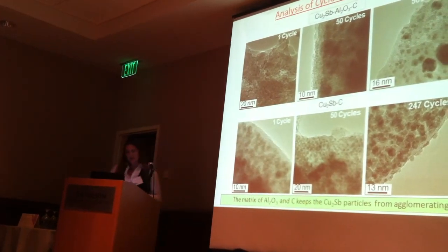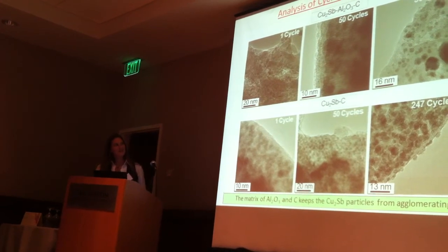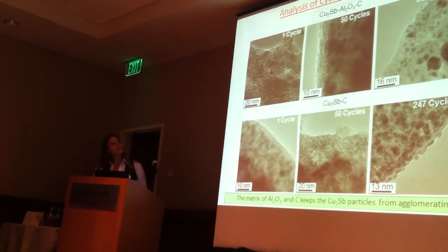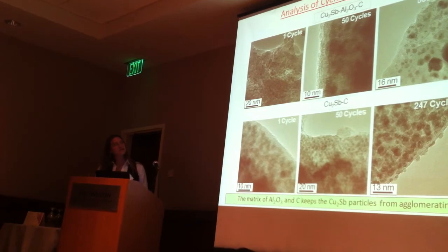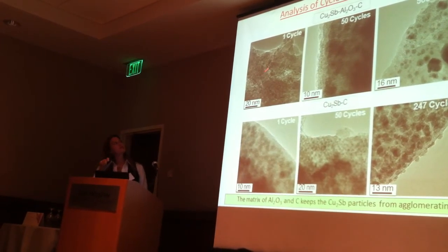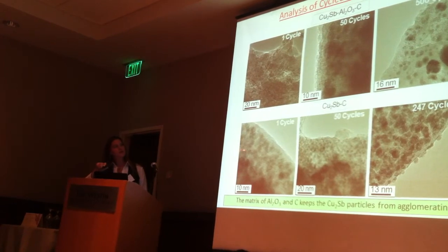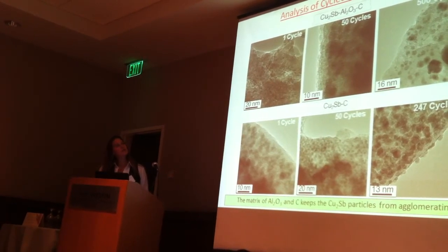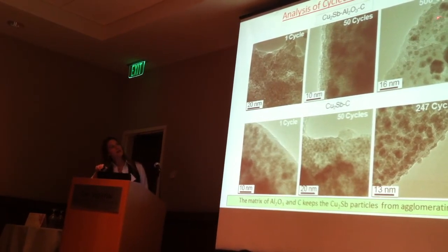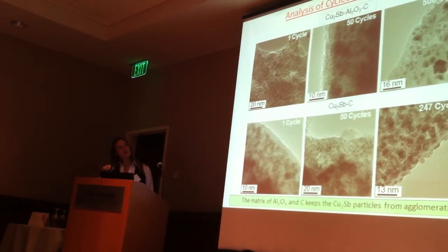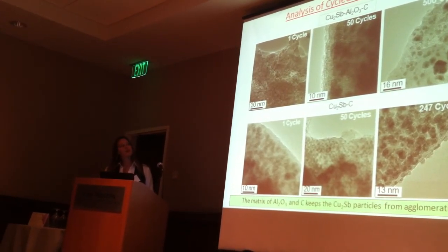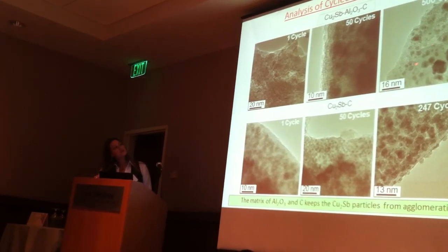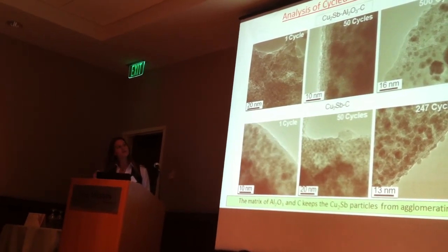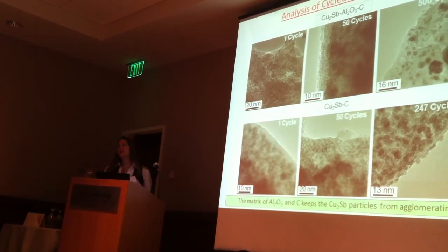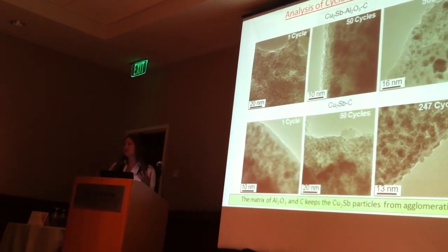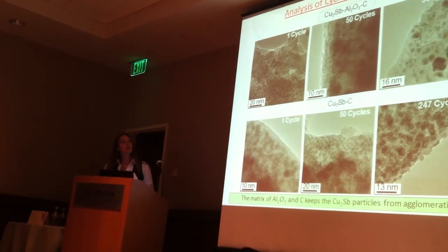Another really exciting bit of data for me was these are TEM images of electrodes that have been cycled for various numbers of cycles. The top row is with aluminum oxide, the bottom row is our alloy without aluminum oxide. And just skipping to the end here, this is the electrode material after 500 cycles. And you can see that these spheres here are crystalline particles, and even after 500 cycles, they're still constrained to about their original size. They're still in the 2 to 20 nanometer range.